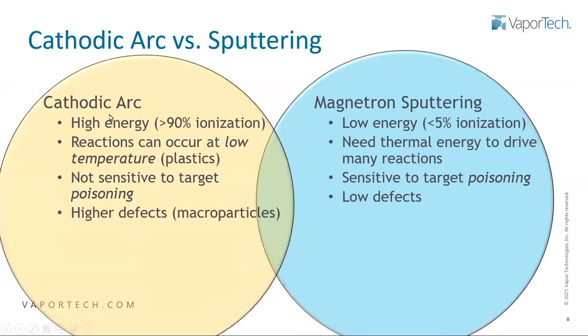So the biggest difference is energy. Cathodic arc is a very high energy process. Most of the material coming off the target is ionized. That's that positively charged aspect that I mentioned before. Magnetron is fairly low energy, with a small amount of ionization. There's ways to boost that with various configurations, but it's still fairly low.